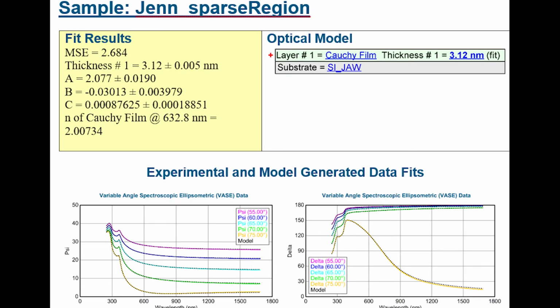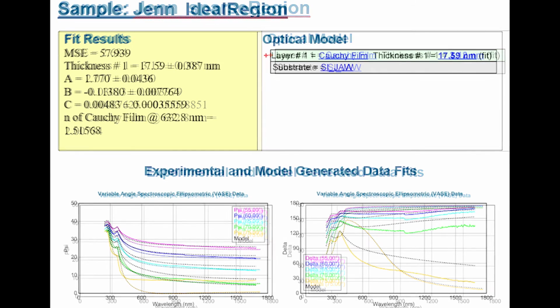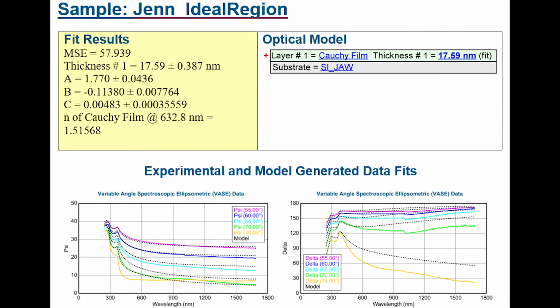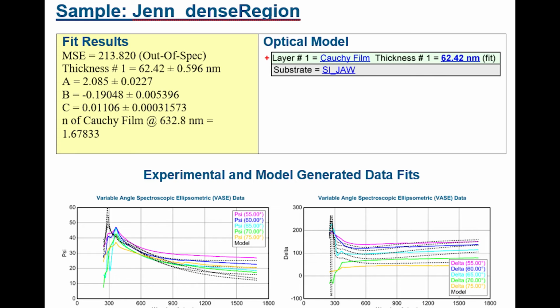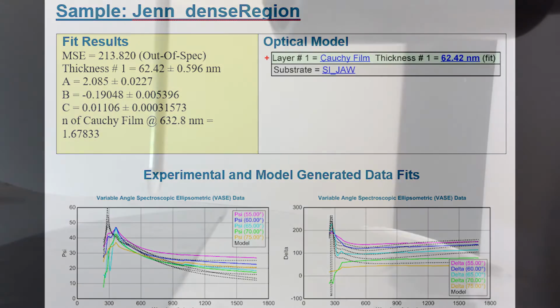For the full test, 3 ellipsometry measurements were taken in 3 different observed regions of the substrate. The thickness of the deposition in a thin region was 3.12 plus or minus 0.005 nanometers. The thickness of the deposition in the ideal region was 17.59 plus or minus 0.387 nanometers. And the thickness of the deposition in the middle of the substrate where the drops fell was 62.42 plus or minus 0.596 nanometers.